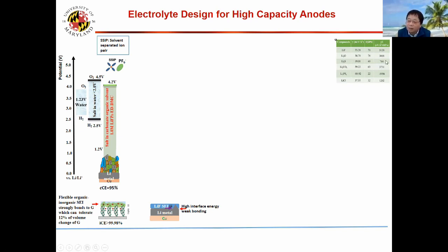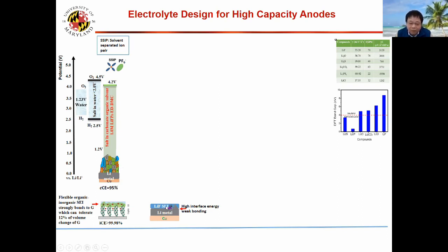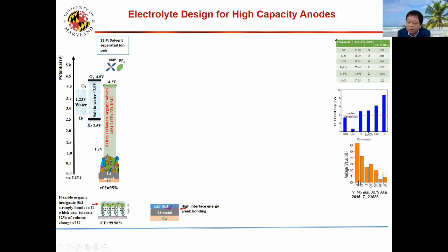Second, we want efficiency to be high, meaning the SEI thickness should be really, really thin. If thick, you consume more lithium. The SEI should also be really electronically insulating. If insulated, they can build very thin because the limiting thickness is the tunneling effect. We check the band gap and lithium fluoride is really broad, meaning its electronic conductivity is lowest. We also have to consider the cathode side. If you have fluorine forming lithium fluoride on the anode side, maybe you have an opportunity to form lithium fluoride on the cathode side too. The electrochemical stability window for lithium fluoride is six volts, so if they form lithium fluoride on the cathode side, both sides benefit from the fluorinated electrolyte.